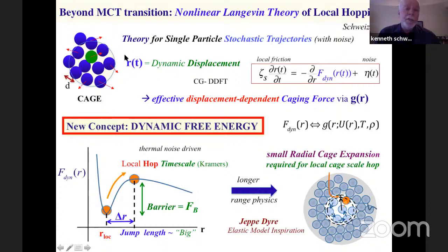And so if you like, the order parameter is actually the dynamical variable, the displacement of a particle from its initial position. And then through both physical arguments and some level of coarse-grained dynamic density functional theory, we came up with this nonlinear Langevin equation theory, which is really a force balance between local friction, noise, and something else. And of course, all the physics is in the something else. It's an effective force that depends on the displacement of any given particle. And it's representing the cage effect. And that effective force using this idea can be constructed from knowledge of g(r) or S(k), just as mode coupling theory. And so it's predictive in that sense.